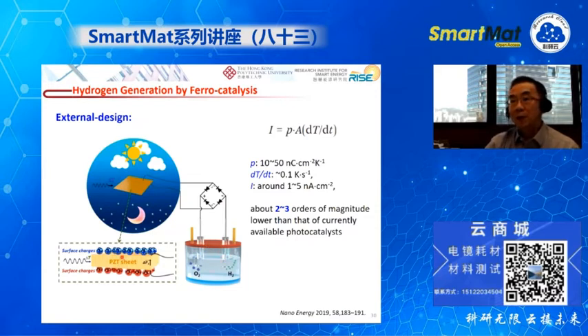But if we calculate the current released due to the pyroelectric effect and compare it to that of the photocatalyst, actually, we found the current released by the pyroelectric effect is two or three orders of magnitude lower than that of the currently available photocatalyst. So in order to make this pyrocatalysis more efficient, we cannot adopt this external design. We have to put the material into the water, and we have to make use of small particles, nanoparticles.